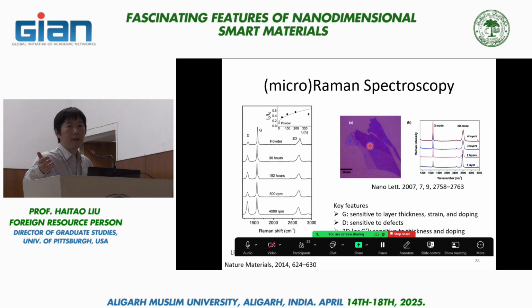You can get a very decent Raman signal by integrating a couple minutes using a milliwatt of signal focused onto a diffraction limited spot. That is actually a very strong Raman response, knowing that you only have one layer of material.